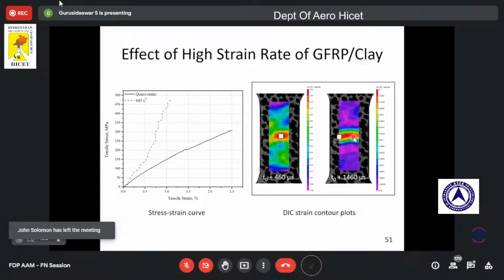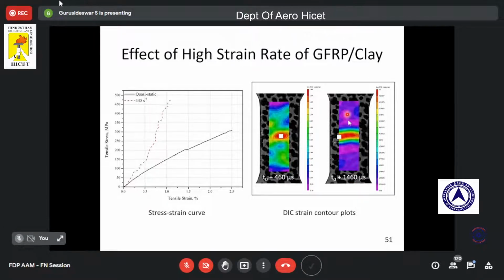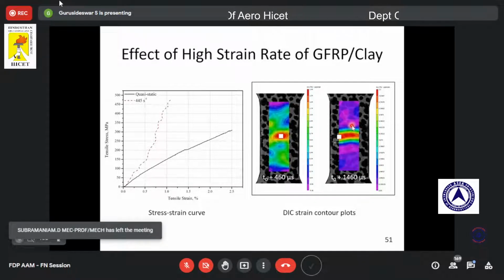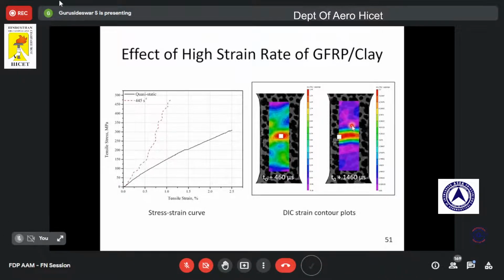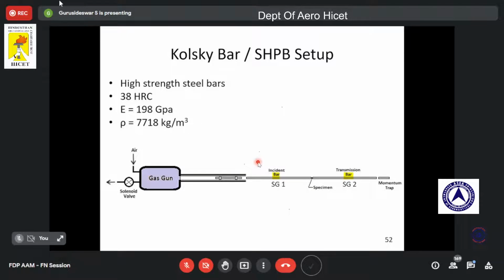We used a high-speed camera to capture images, because, as you all know, the loading happens in microseconds. So I cannot use a normal camera. I need to use a high-speed camera so that I can have an image for every 10 or 1 microsecond. With the help of the high-speed camera, we were able to get images at every 10 microseconds, and then we did the post-processing of the images, and we got this strain contour plot. With the help of the strain data, we could plot the stress-strain curve of the sample at high strain rate. Yeah. So now I have come to the end of my talk.